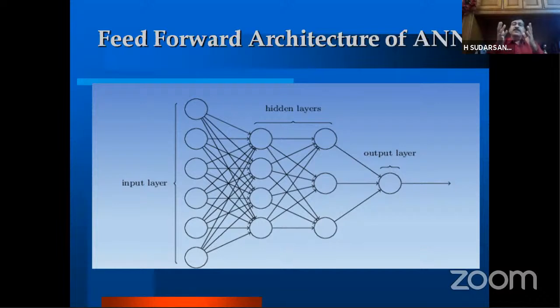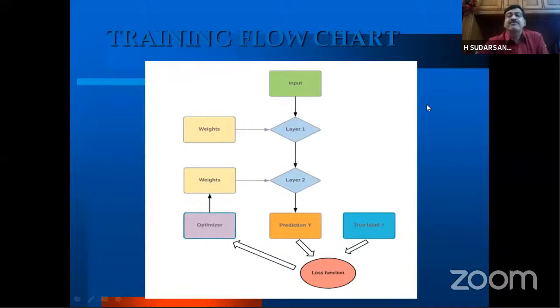Once you are satisfied with the mix proportioning using your artificial neural network predictions, you can now actually cast and do the trial. So what is happening? The trials are reducing considerably. With the help of ANN, you are able to reduce the mix design trials that are required to design the high performance concrete.